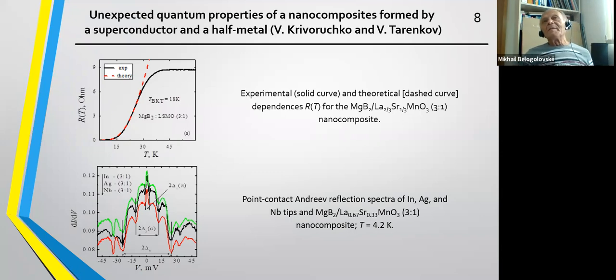So it was a manganite with nearly 100 percent spin polarization. What was unusual is a huge difference in the sizes of superconducting grains and half metal grains. The difference was at least 2 or even 3 orders of magnitude. The diameter of superconducting grains was about 5-10 microns, and the size of the manganite grains was about 10-15 nanometers. You can imagine it as a great superconducting ball, around which there is a shell of strongly ferromagnetic material.